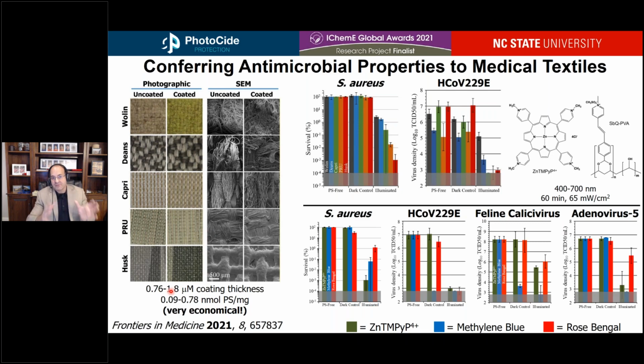Because we're just coating the surface of the fibers, we have a very economical use of our photodynamic agent, about a 10 to 100-fold improvement in the level of the photosensitizer present in terms of cost savings. And so this enables us to translate what is usually the most costly part of a photodynamic material, the photosensitizer, to being scalable for manufacturing processes, because now we've hit the cost savings needed for deploying these products and these coatings into the marketplace.